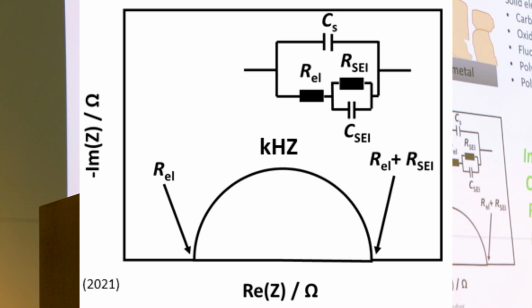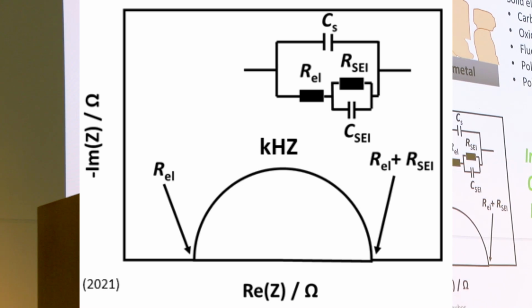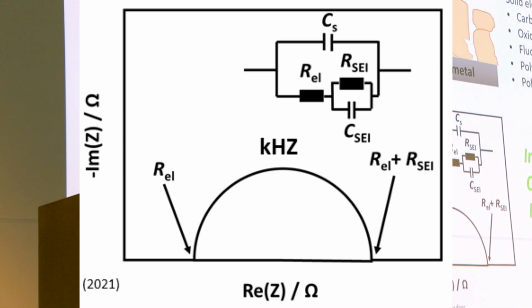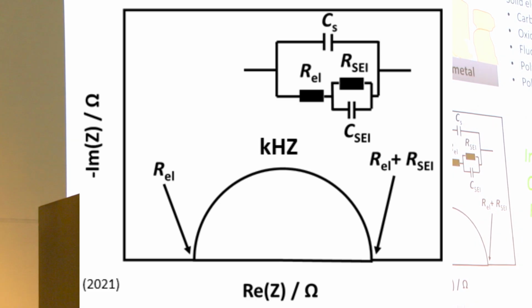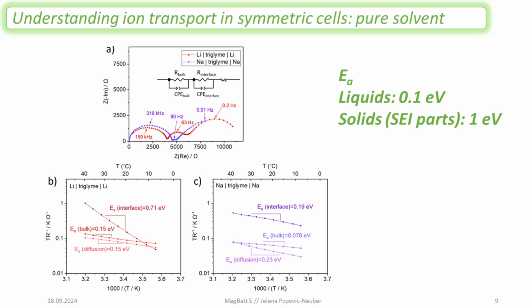This is not new. This is something that is known from corrosion since the 70s, and it's also something that Doron Aurbach did very extensively in the 90s on lithium metal. So what do we see from these kinds of experiments? First, we can very nicely distinguish different contributions: in the first semicircle the bulk, in the medium semicircle the interface, and then the lowest part is actually the Warburg diffusion, where we can extract the transference number already from the bulk.